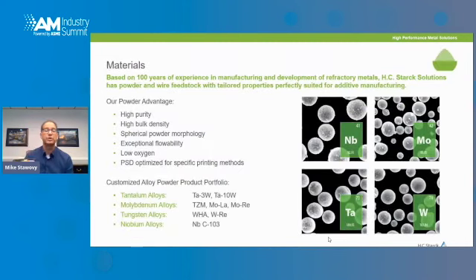So if I want to focus on some of these key areas, I'll start with the materials and what we can offer in these refractory metals from HC Starck Solutions. In terms of focusing initially on powders, we can obviously produce the pure elemental powders, so niobium, molybdenum, tantalum, and tungsten. We can do these in ways that they have high purity, high bulk density, good spherical morphology, good flow, low oxygen, and the right kind of particle size distribution that fits with the different AM technologies.